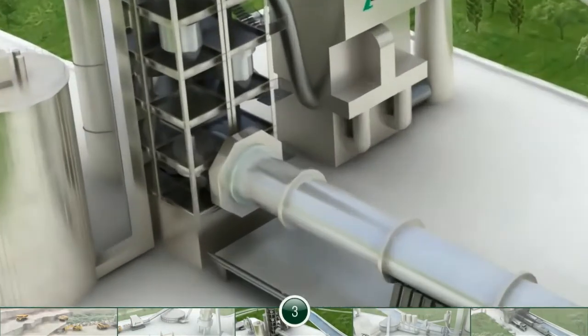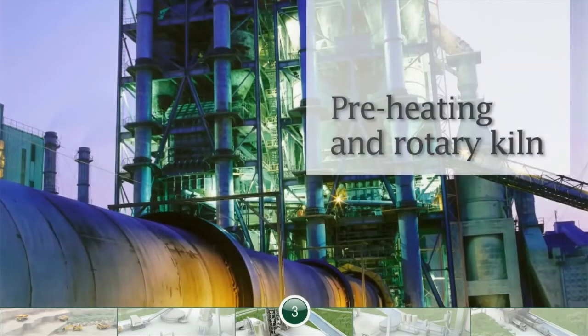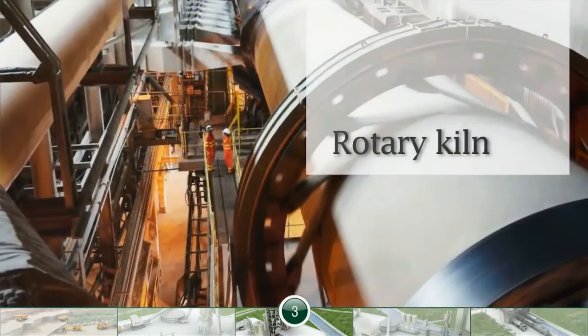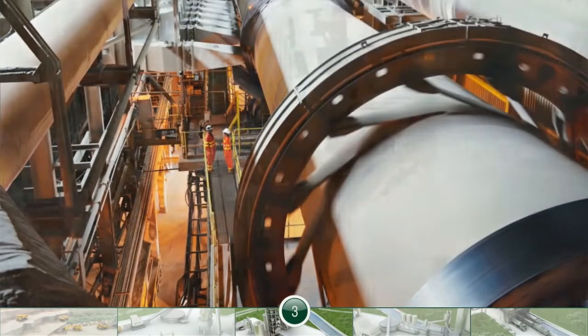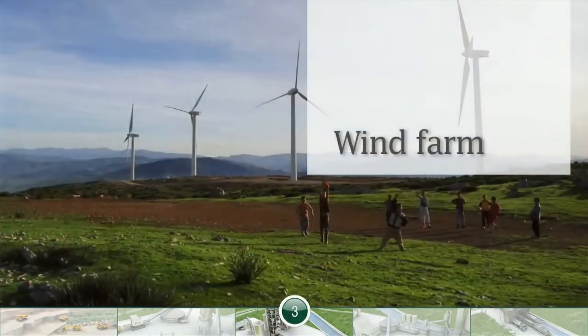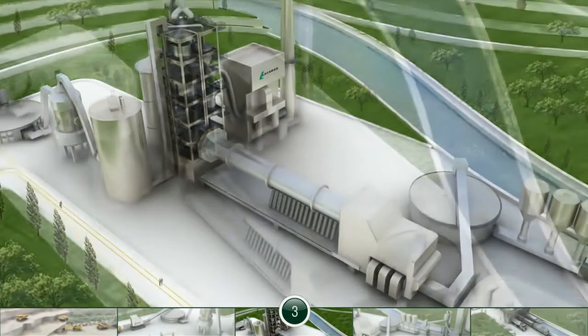Raw mix is preheated to 800 degrees centigrade, then heated to 1450 degrees centigrade in the horizontal rotary kiln. The fired materials take the form of hard granules called clinker. Lafarge has made a commitment to WWF to reduce its global CO2 emissions, so uses alternative fuels, for example.